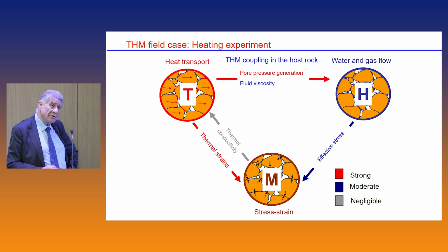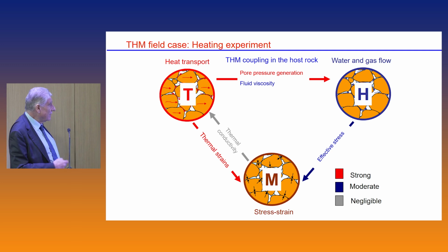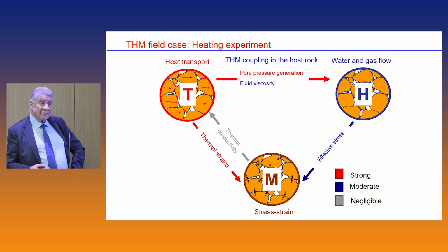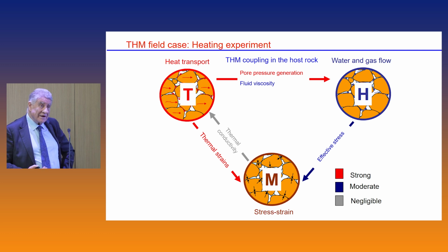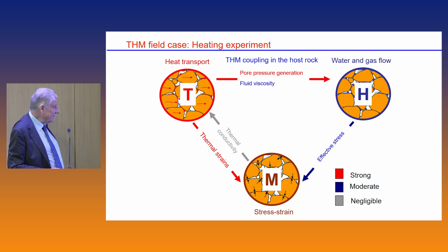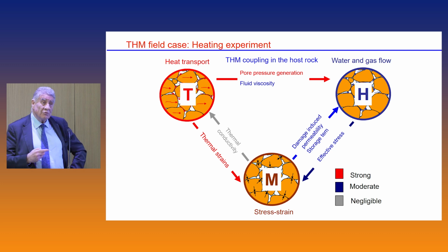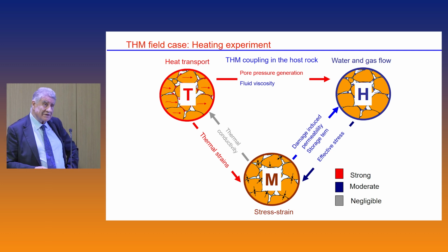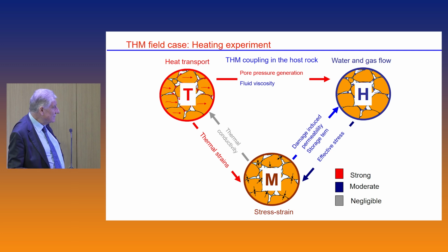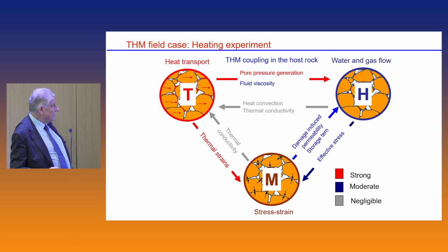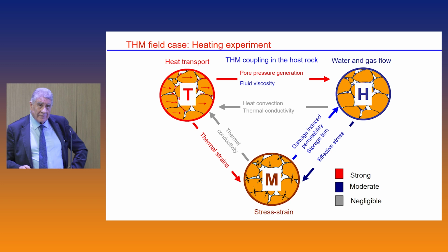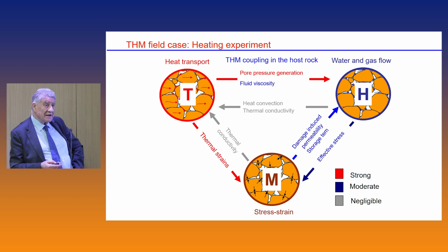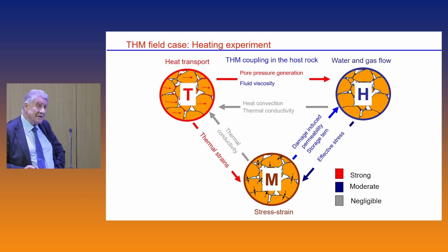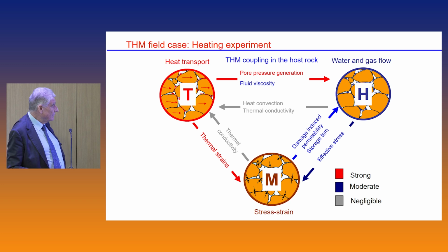If we do this same route in the opposite direction, obviously there is a strong coupling from the temperature to the thermal expansion of the material, more moderate from mechanical to hydraulic through the variation of permeability with plastic strains or with damage in this case, and again from the hydraulic to thermal, because heat convection is negligible, there is no change in thermal conductivity, so that coupling is negligible.